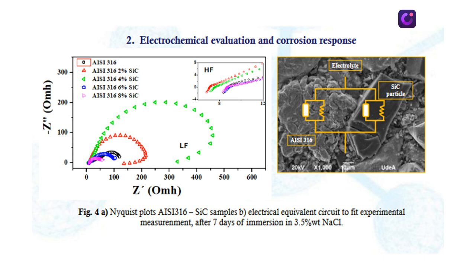In this order, the 2% silicon carbide content showed a drop in the capacitive arc around 150 ohms. These two materials are the ones that presented higher capacitive arcs than the sample without reinforcement, which falls at 90 ohms, indicating less electrochemical activity given the microstructural characteristics. On the other hand, the 6 and 8% silicon carbide reinforcements show high electrochemical activity and thus small capacitive arcs with ohmic drops of 50 and 25 ohms respectively.